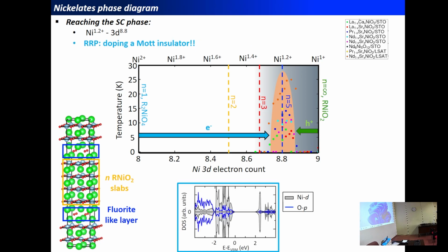And effectively, if you start from the left part of the phase diagram, from the n equals 1 member, and you look at the projected density of states in this material, so on the nickel d states and oxygen p states, we end up with a very nice Mott insulator in which a band gap of approximately 2 eV is formed between the nickel 3d states. And therefore, reaching the superconducting region starting from this side requires electron doping a Mott insulating starting material, which is more compatible with what is done with other oxide superconductors.